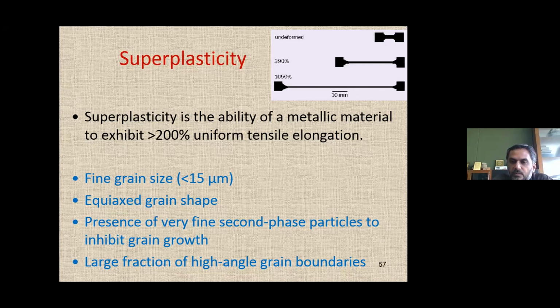Now, why are you getting that superplastic behavior? Because with the help of the FSW tool, you have done the processing in that region. And because of that processing, there is an extreme grain refinement. You have very good uniform grain structures. At the same time, the precipitates you had earlier in the parent metal were also fragmented and distributed more uniformly into the matrix. And because of that stirring and mixing, you have a large amount of high angle grain boundaries. These are all the things which you are achieving while doing friction stir processing, right?